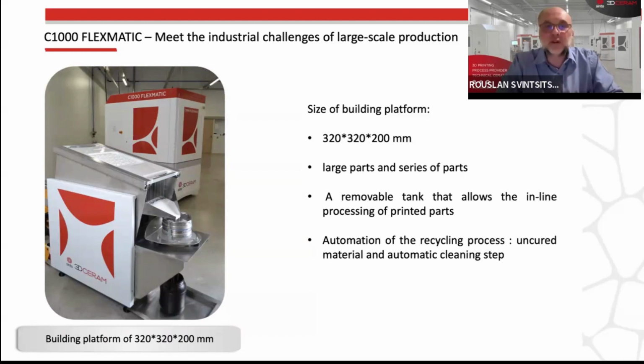So typically, the slurry goes by gravity after the printing to the recovery tank, and this slurry is recycled. It is filtered with a mechanical filter to avoid any small pollution particles, any clumps. And this slurry can be used for the printing again. So the process is semi-automatic. This trolley with the vibrating screen and recovery tank is supplied with the machine.